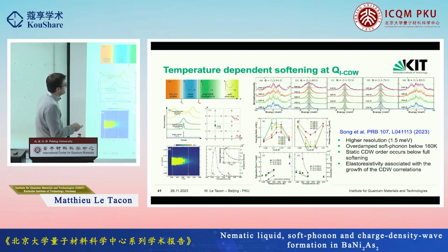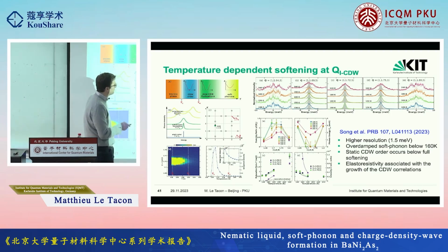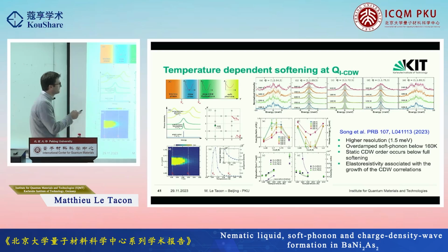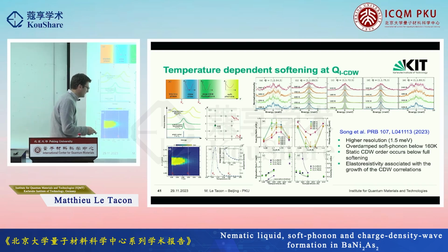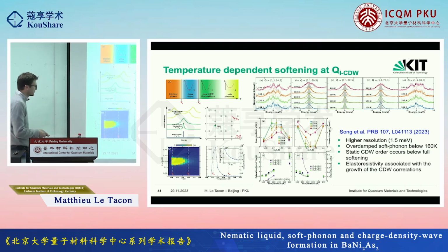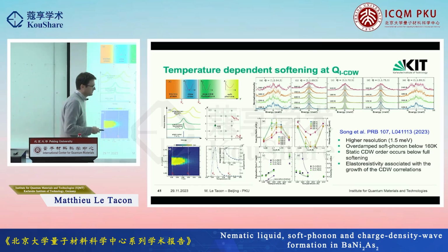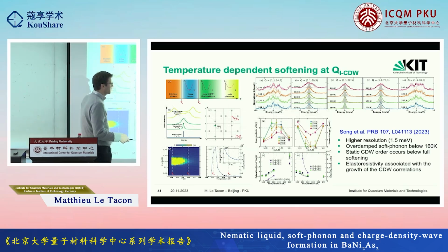In parallel to our measurements, the group of Birgeneau also published a very nice study with somewhat higher resolution, from which they basically claim that the full softening of the mode is occurring at a temperature which is already larger than that at which the charge-density wave really forms. It might be, it might not be. I mean, that's their claim. And based on the data that we obtained, we can just not conclude whether this is true or not because we don't have sufficient resolution.